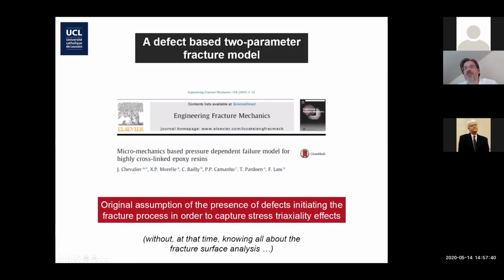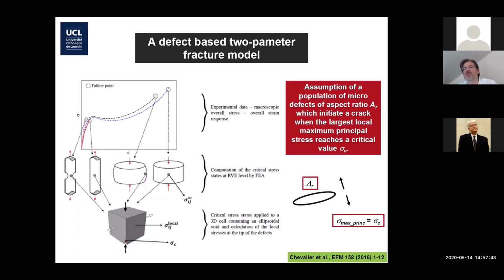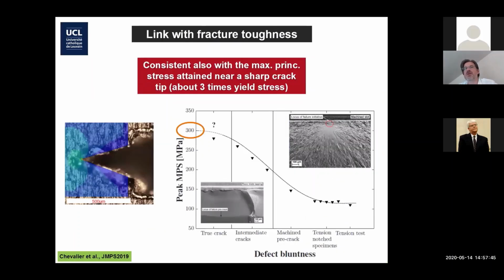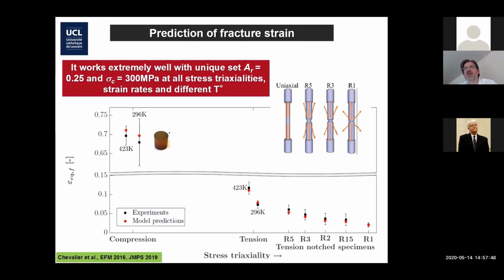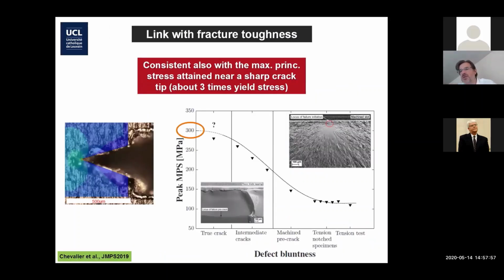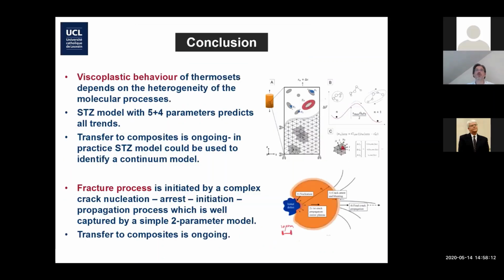The last 4-5 slides that I will skip show you the model that we have developed, and there is a simple model to predict this effect just based on 2 parameters: an aspect ratio of defect and a critical stress of about 300 megapascals, which can be used to rationalize the notch test, tensile test, the compression test, as well as the fracture toughness specimen. All right, I'm going to go to the conclusion, not to be too late.